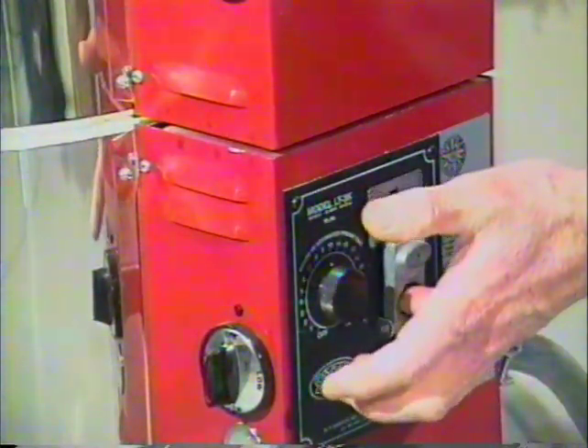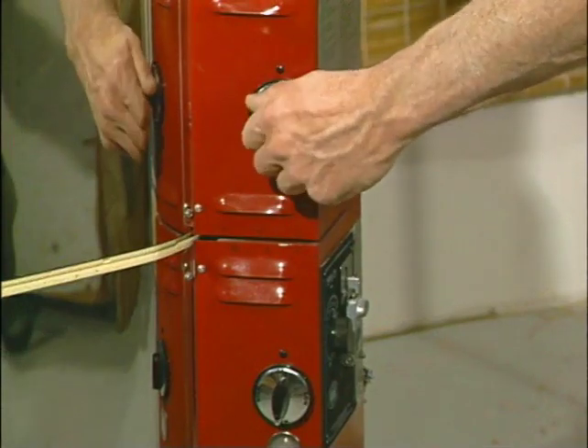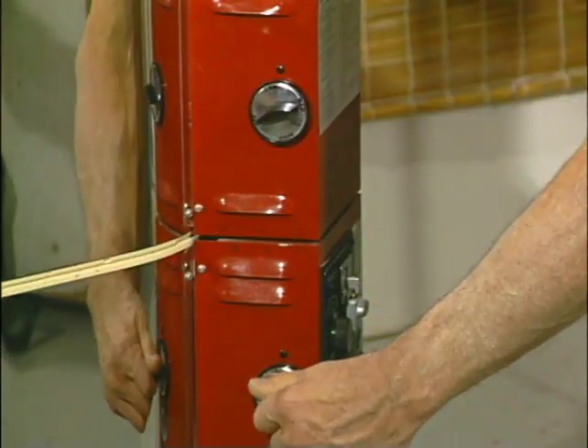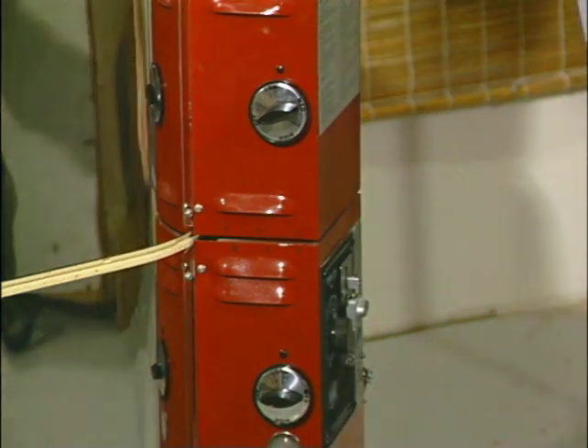Arm the firing button in the kiln sitter. Turn the elements onto low to begin, and then we'll turn it up gradually until we've achieved temperature. You can see that the first cone is down flat, and the target cone indicates that we've reached temperature. We can turn the kiln off now and let it cool overnight.